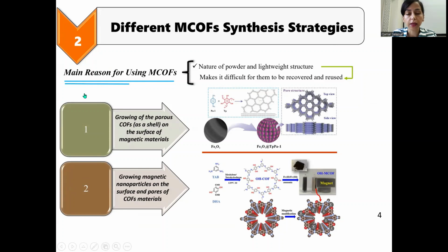In general, there are two main synthesizing strategies for preparing magnetic COF. In the first one, by growing the porous COF as a shell on the surface of magnetic material, the final product is achieved. And in this process, as you can see in this picture, first of all, a magnetic particle like Fe3O4 is synthesized, and after that the surface of this material is functionalized with other organic groups, and then in the last step, the COF layer is coated on the surface of the magnetic material.